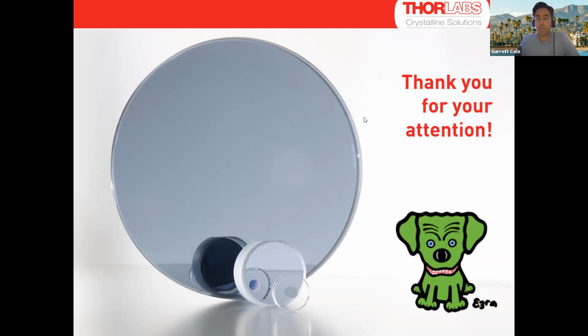Another question about how robust are these? Fairly robust. Again, we don't do other coatings, so I don't have a good comparison, but a properly bonded structure will survive a tape test and they don't degrade. They're not hygroscopic, so no water gets into these. Gallium arsenide based materials are pretty stable. Like I said, temperature can be a problem if it's a large mismatch with the substrate, but we usually tell customers what the bounds are. Like heat this optic to 150 only or below, or this one to 250 C and below, and so on.